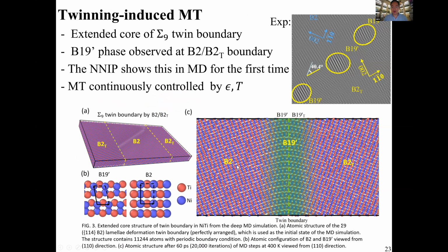So typically when you have a twin boundary, a symmetric twin boundary, you would have a highly coherent twin boundary. But in our case, in the MD simulation, we have this reconstruction which goes into this B19 prime-like structures. And the grain boundary actually has this kind of a curvature, which is highly unusual. And that actually turns out to have experimental validation.